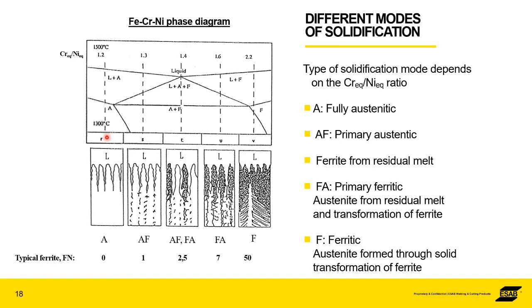And what we're trying to illustrate here, it's an old diagram. The solidification that you get, depending upon the chemistry, can either be fully austenitic, for example. So we've got a fully austenitic, so there's no ferrite in there, compared to the other end of the scale, if you like, where you've got fully ferritic. So all of this is austenite and all of this is ferrite. And then in between, you've got transformations from austenite to ferrite, a mixture of the two, or from ferrite to austenite.